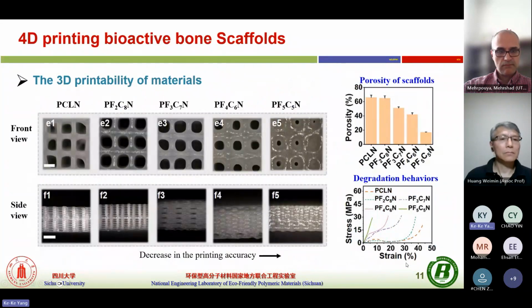We also evaluated the 3D printing ability of these copolymers. Besides the filament density, composition also affects the porosity of the scaffold. If we increase the PBF segment, printing accuracy will decrease.